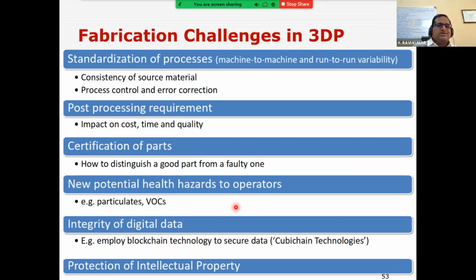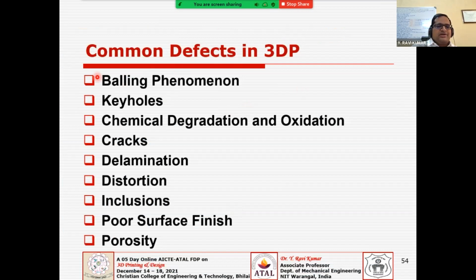So like this, you can keep on talking about certain fabrication challenges and some common defects which you can come across. Some balling effect because of the different surface tensions between the melt pool and the adjacent powder, some keyholes, or chemical degradation or oxidation, for which we need an inert environment or vacuum. Then cracks can be formed for several reasons. Delamination between the substrate and the part or within the layers, a lot of distortions, shrinkage, warpage, inclusions and poor surface porosity. So you have several common problems or defects you can come across. So how do you overcome these defects? Definitely it is a challenge for you as a user.